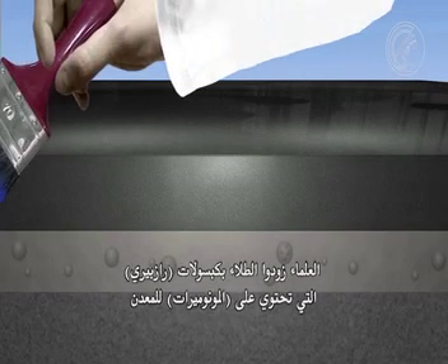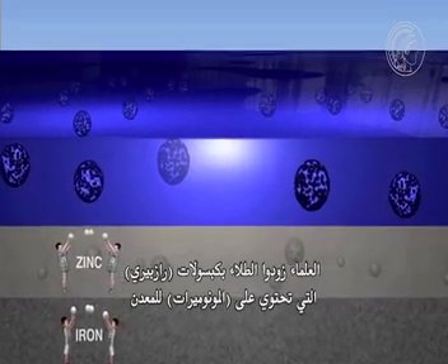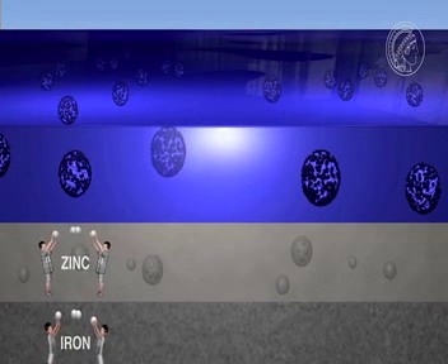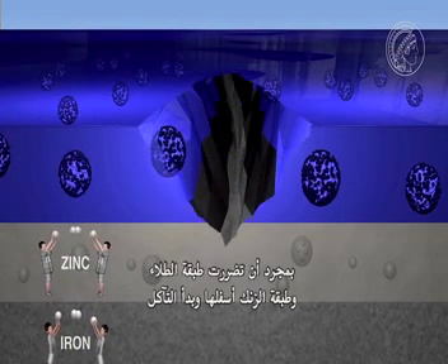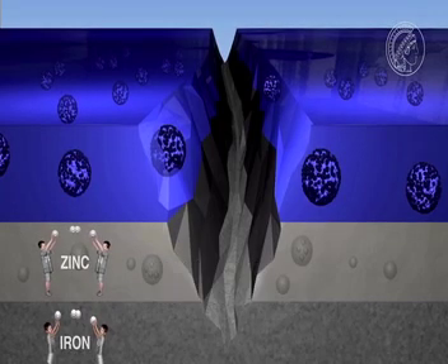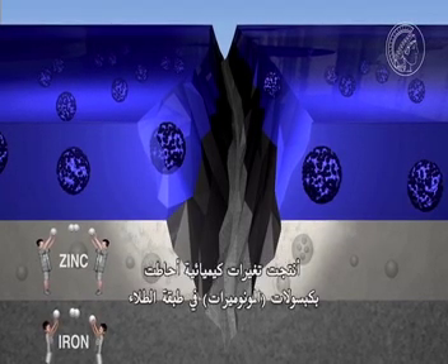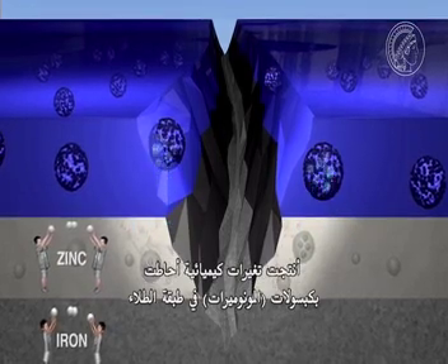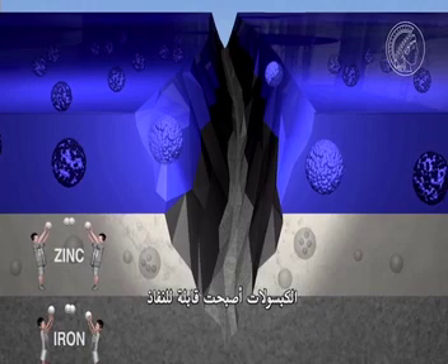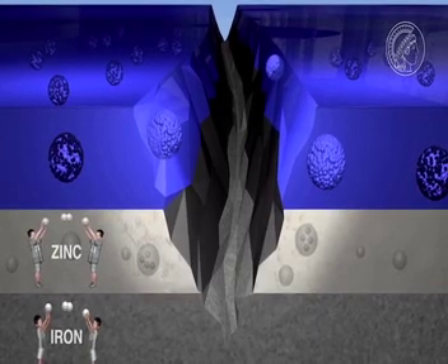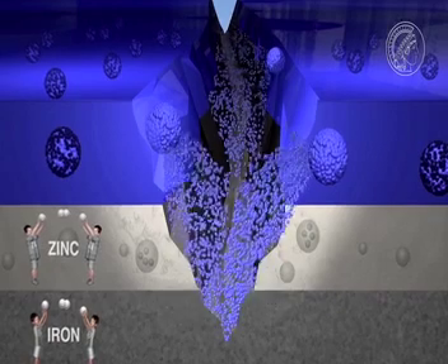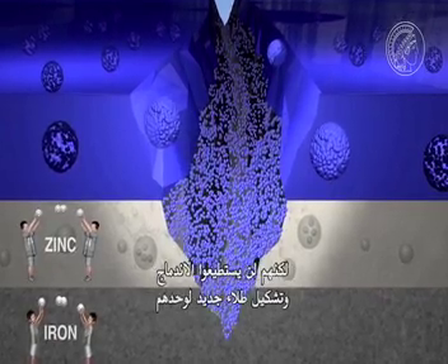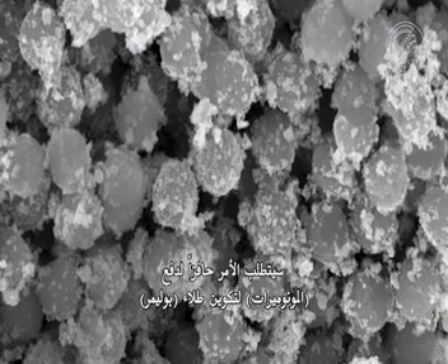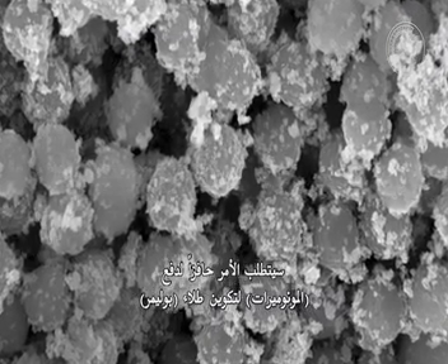The scientists supply the varnish with the raspberry capsules containing the monomers to the metal. As soon as the varnish and the zinc layer beneath are damaged and corrosion begins, the electrons which separate out of the zinc layer produce chemical changes in the casings surrounding the monomer capsules in the varnish. The capsules become permeable. The monomers are released, but they will not be able to combine to form a new varnish on their own. It will take a so-called catalyst to enable the monomers to form a polymer varnish, and that is directly beneath the layer of varnish, hidden in the layer of zinc.